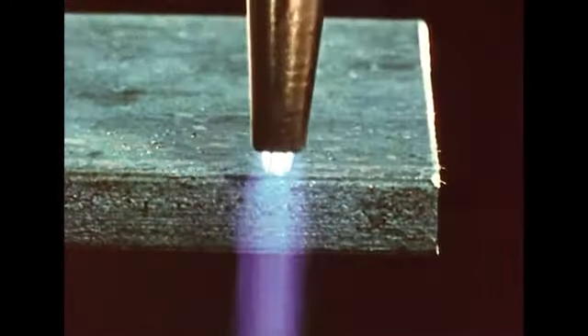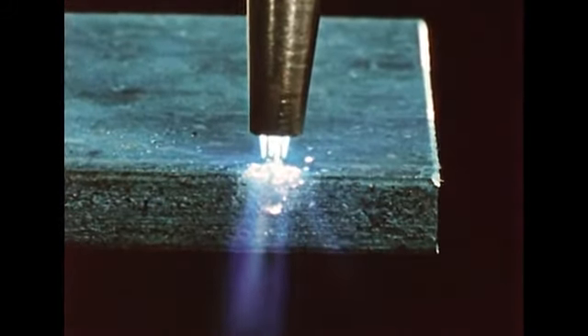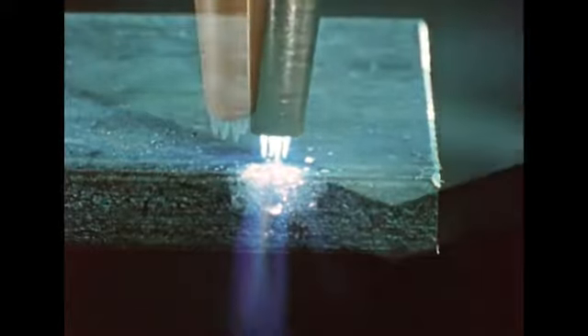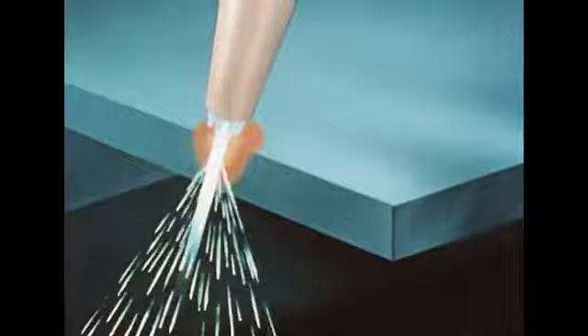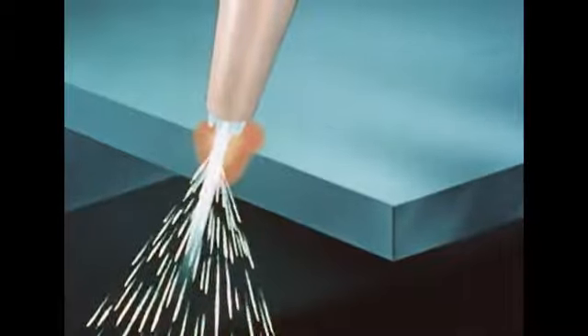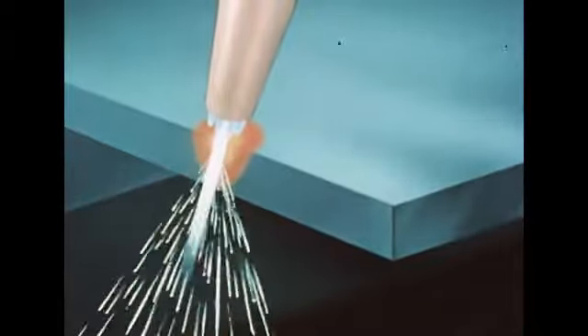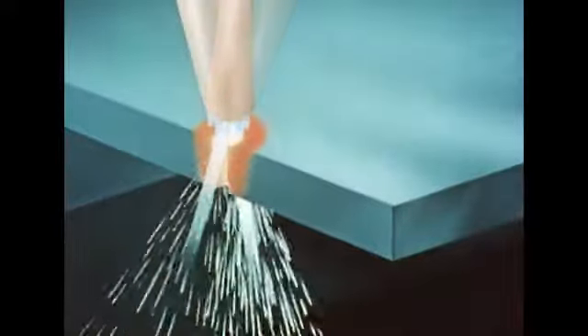Hold the flames over the start of the cut to preheat both the top of the plate and the side edge. Here's what happens. The preheat flames bring a small spot of metal almost to the melting point. Then the cutting oxygen stream is directed against the spot. As molten slag forms, it is blown away by the pressure of the oxygen stream. The metal along the line of cut is removed, leaving a slit or kerf.